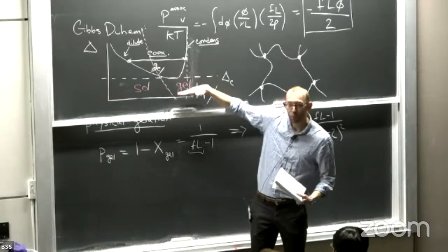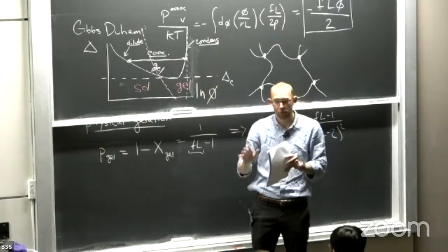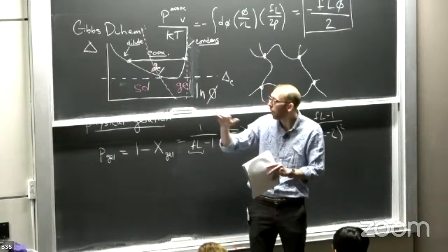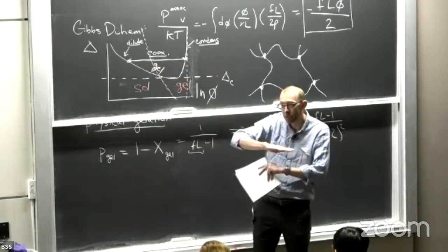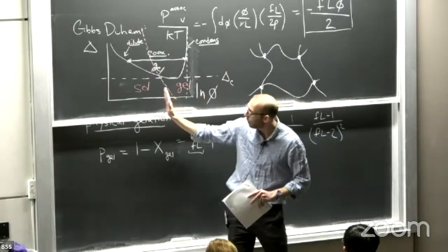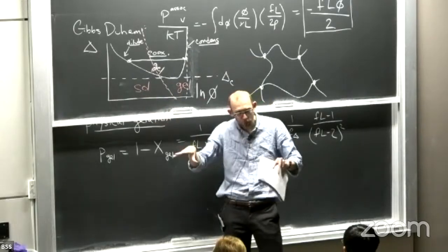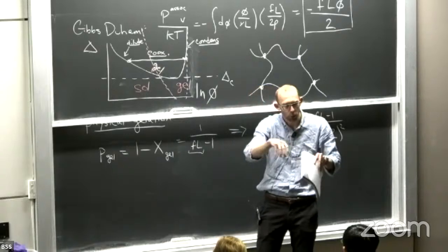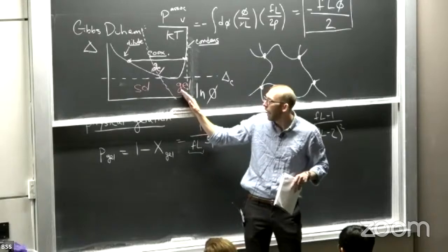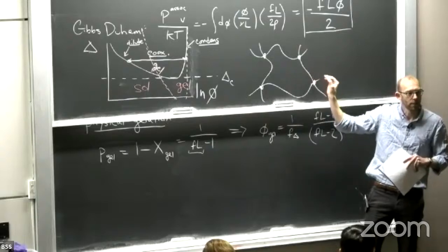Let's consider what happens if you're below this critical binding strength, right? You don't form droplets. You don't have different regions of the system with different polymer concentrations. We're below a critical point, so the polymer concentration is the same everywhere. However, if your concentration is below this pink dash line, then you will have everywhere in the system individual polymers or small polymer clusters. You go above this point, and you have a system spanning network. So your entire system looks like this.